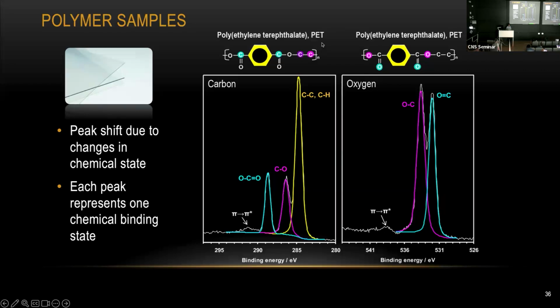And we go ahead and do the high resolution scanning for carbon and oxygen. And you can see all the additional peaks right here. All these peaks belong to carbon, but with different binding energy. So depending on what you have, the first yellow peak you're seeing here, that's a carbon C-C, C-H bond. Right here, around 286, that's C single O bonding. And right down here, C double O bonding, that's around 288.